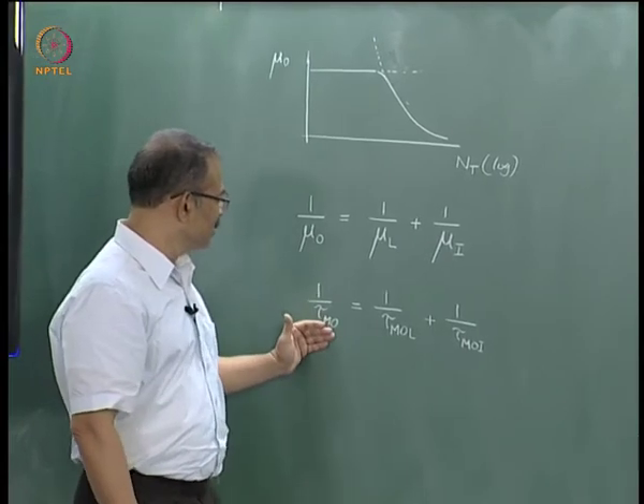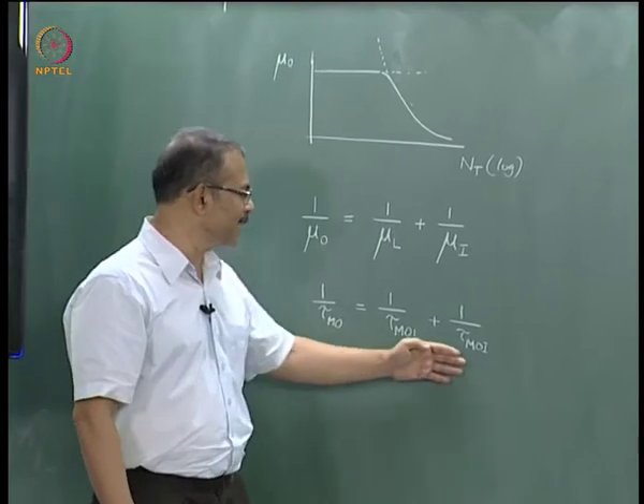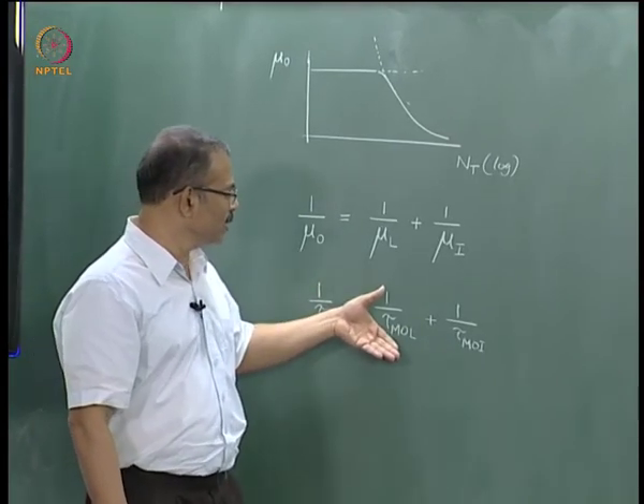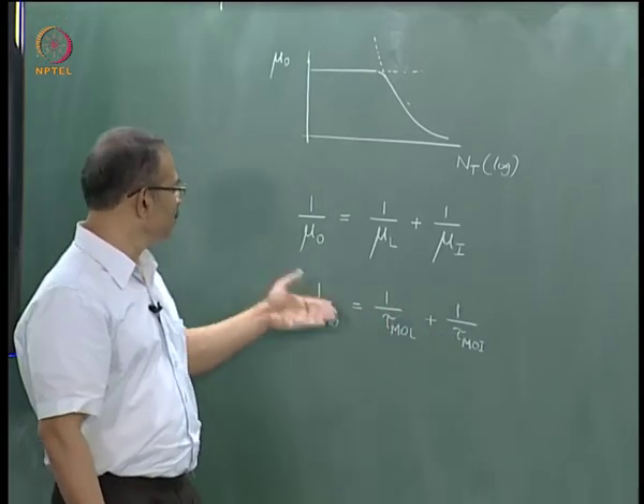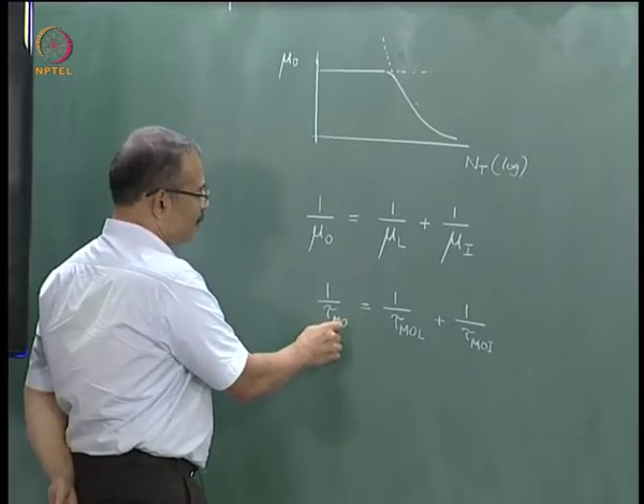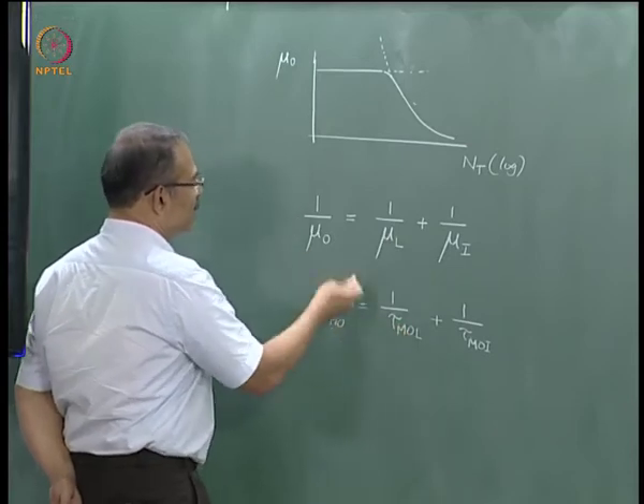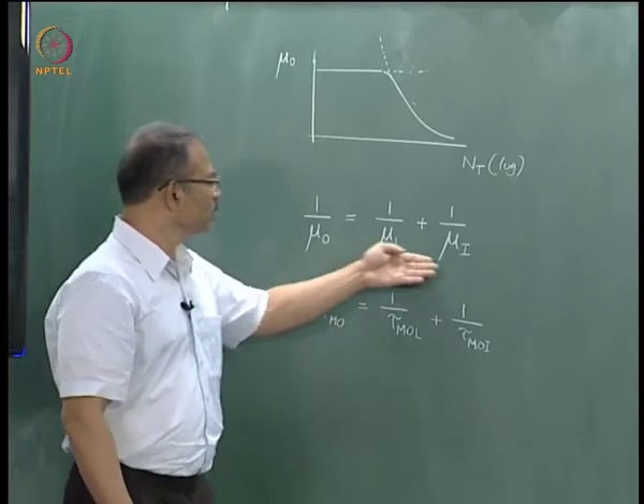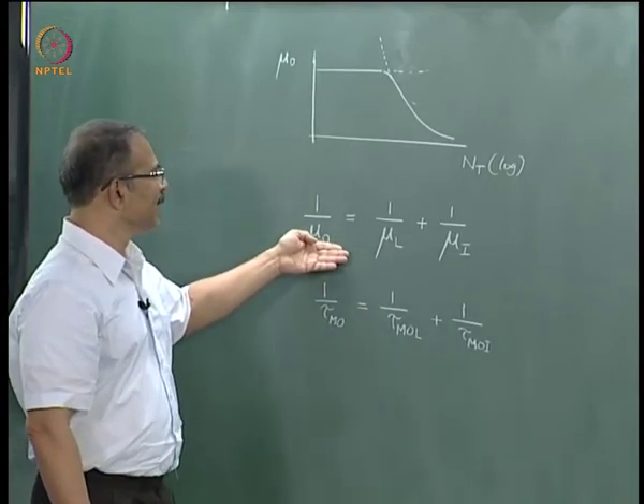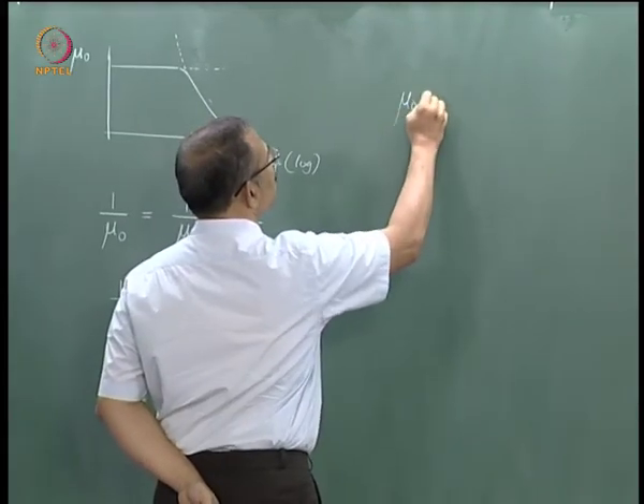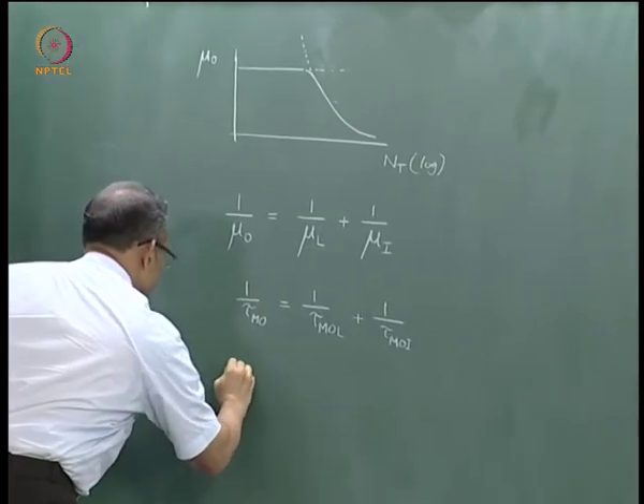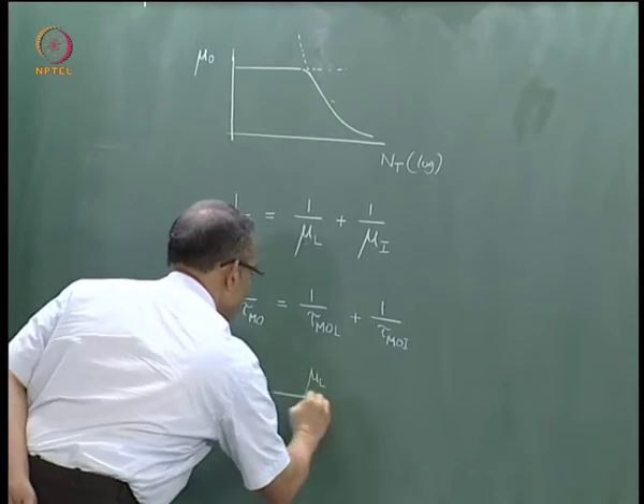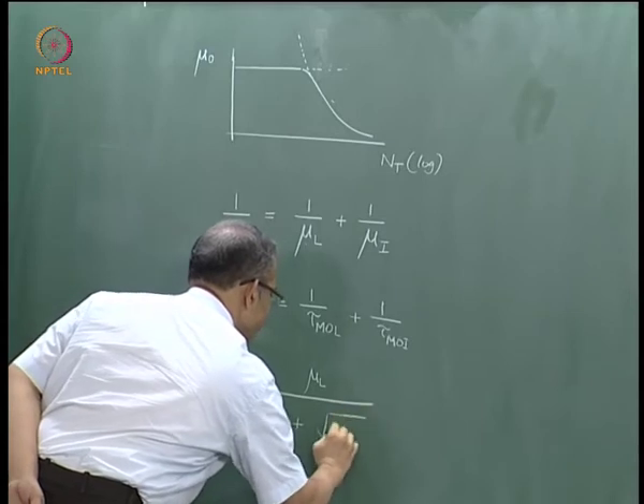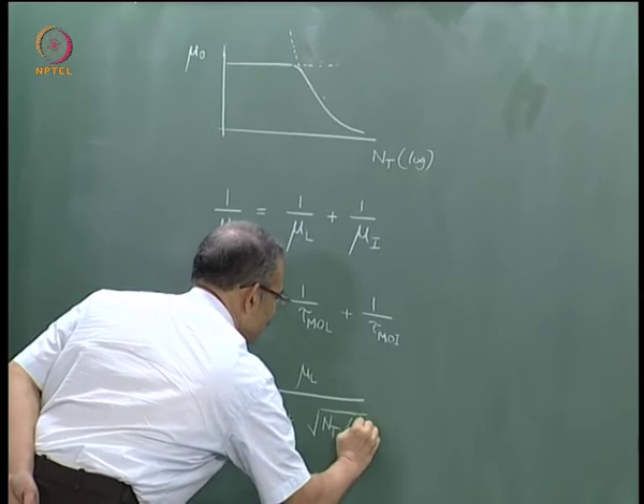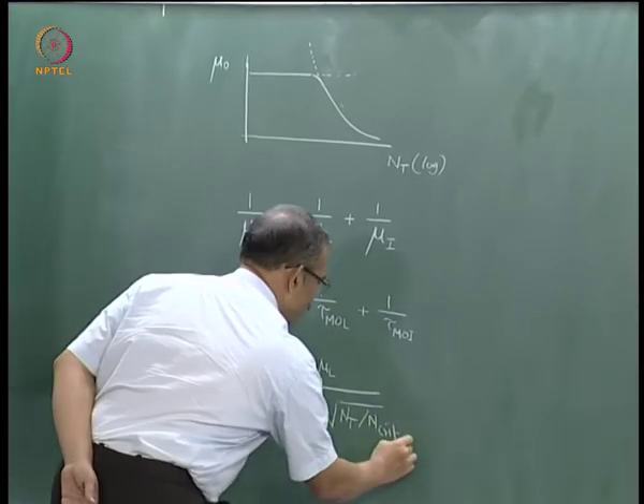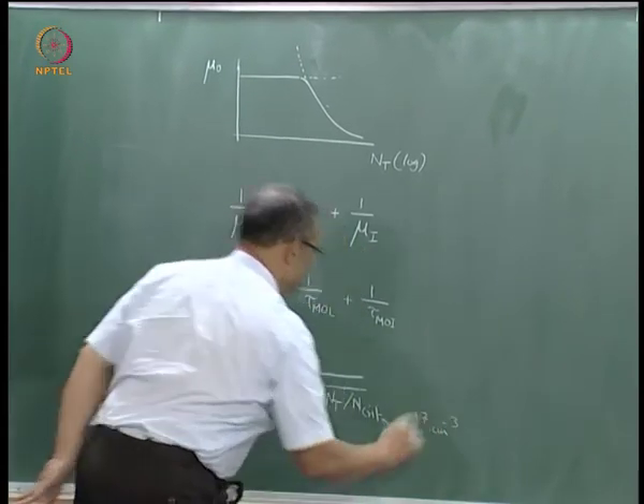So since this formula can be recognized to be valid, at least approximately valid very easily, where the total scattering rate is equal to the sum of the scattering rates of each individual mechanism, and since the mobility mu is proportional to the momentum relaxation time, right, corresponding momentum relaxation time, this formula follows from this formula. Okay. Now once you know this, we can easily get the equation that we have got. So the equation was mu naught, let me write it here, mu naught is equal to mu L divided by 1 plus square root of Nt by a critical doping. It happened to be 10 power 17 per centimeter cube.